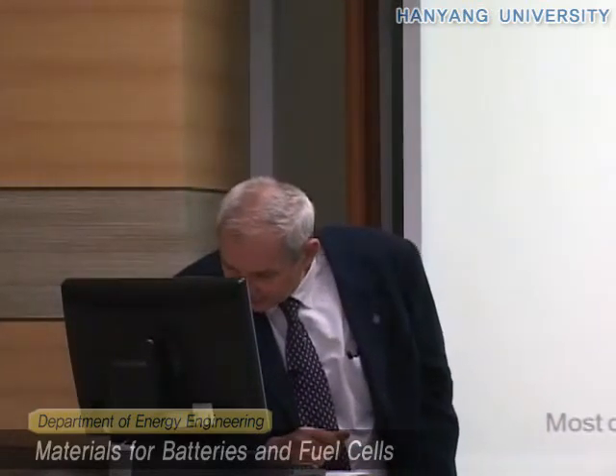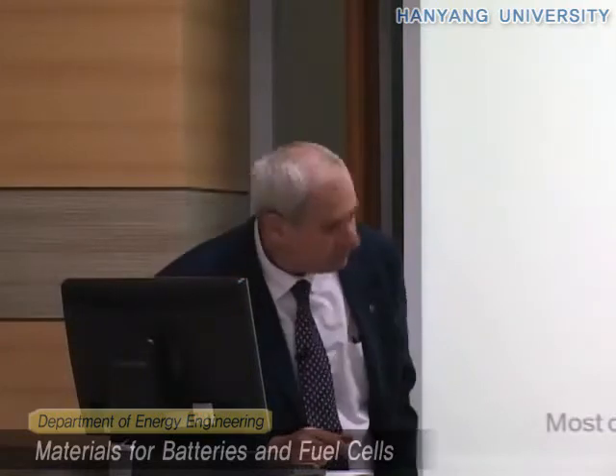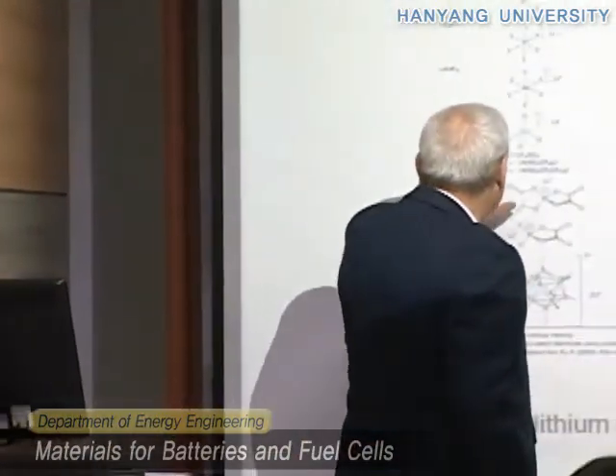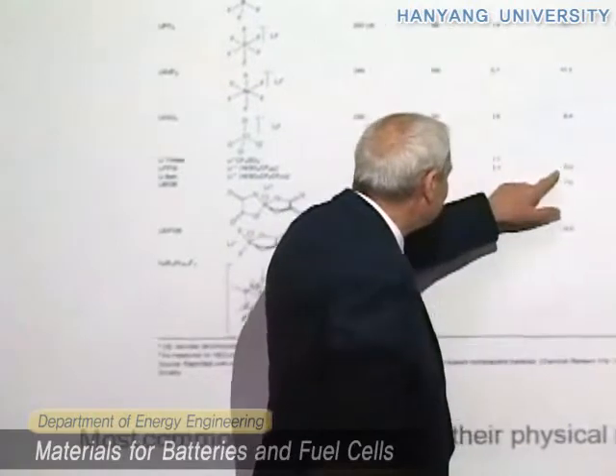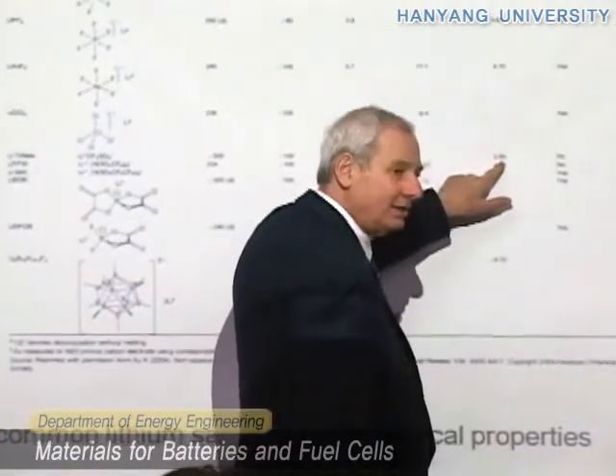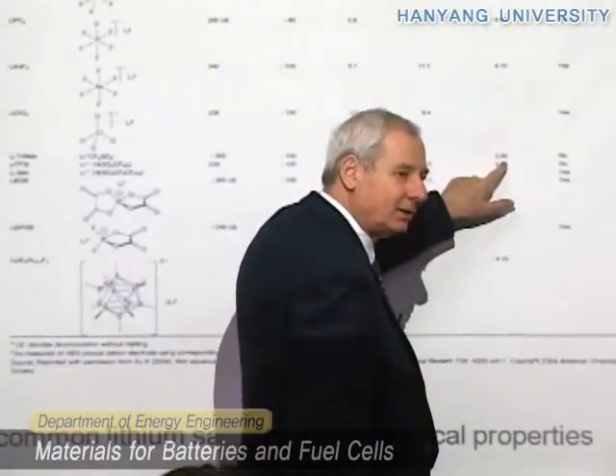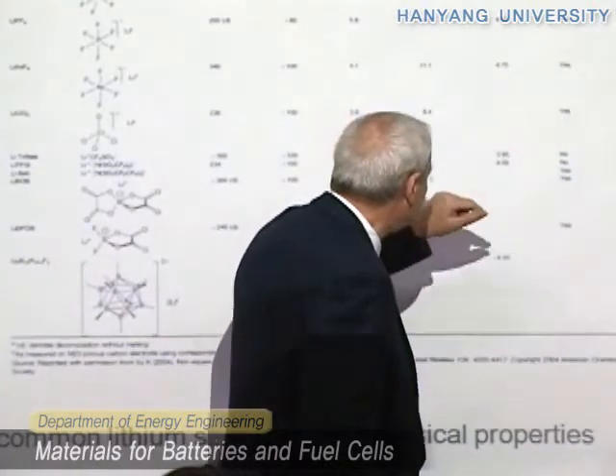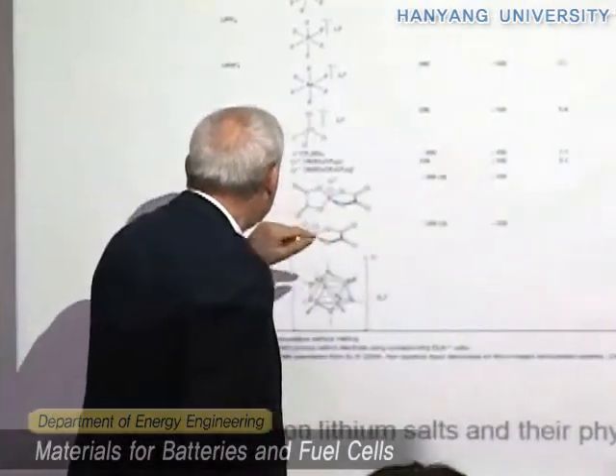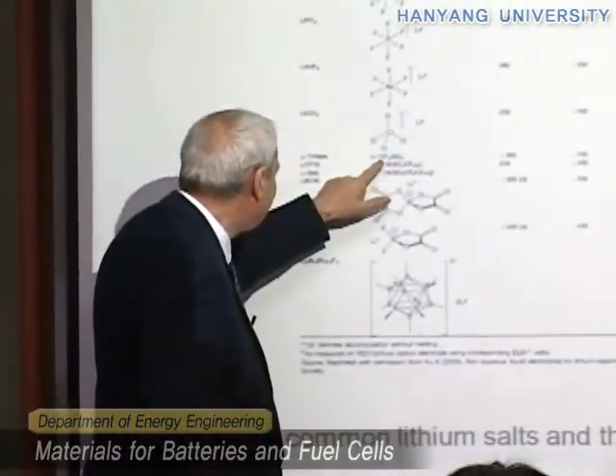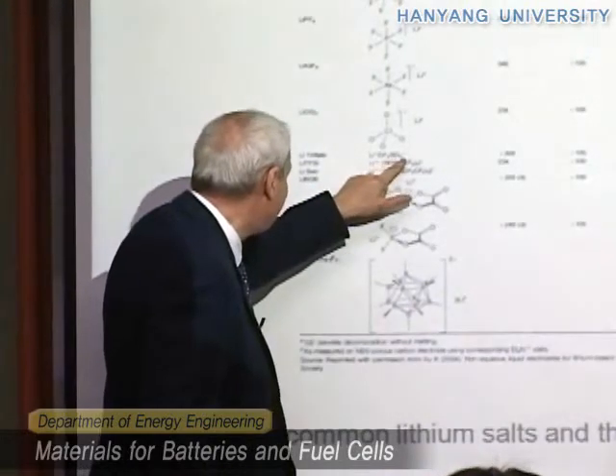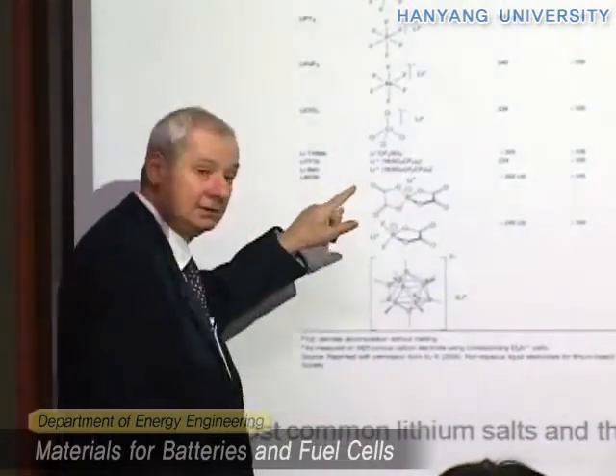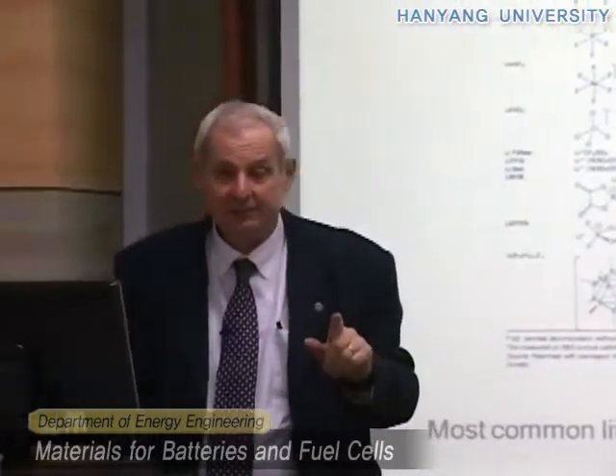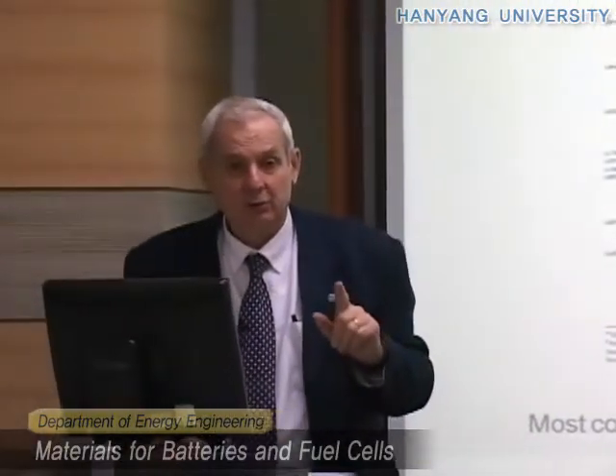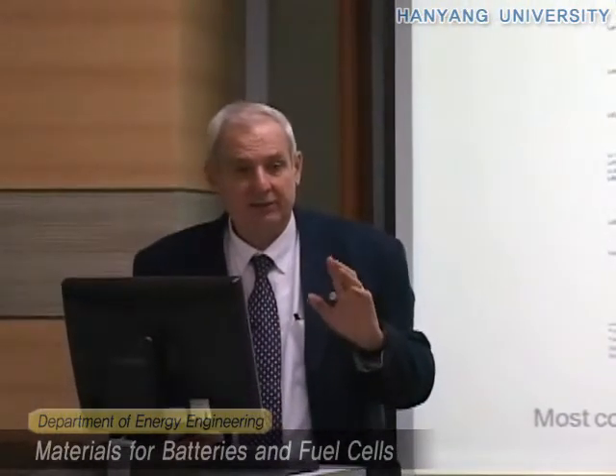For instance, in the case of this one, the decomposition is only 3.90. So this salt is not very used. LiCF3SO3, called triflate. So this one you should not use, because I told you that the cathode materials are deposited on an aluminum substrate.